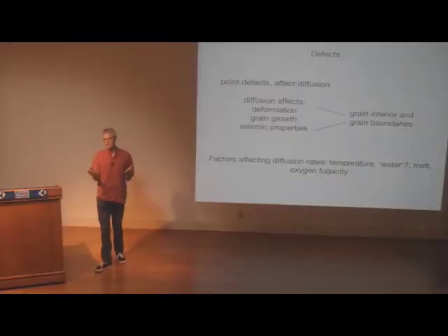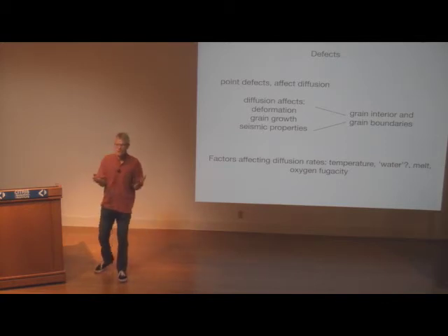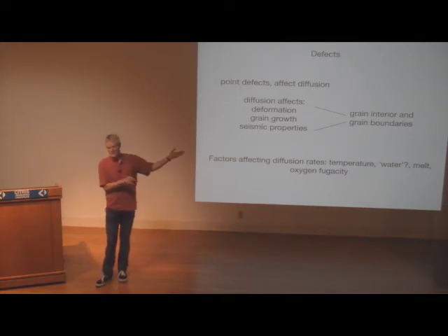I mean, there's no direct way. When we do Fourier transform infrared spectroscopy on polycrystals, we certainly also shine the light through the grain boundaries. But the grain boundaries, you saw the images. If you calculate, as if the absorbance correlates to path lengths in the crystal, in a polycrystal material what the path length is of grain boundaries, you just never see that, because the path length through a nanometer grain boundary, even at a 10 micron crystal, is negligible. So there's no direct way that I know of with which you could determine hydrogen content, hydroxyl content in a grain boundary. So you really have to rely on very indirect measures, such as the seismic property experiments.